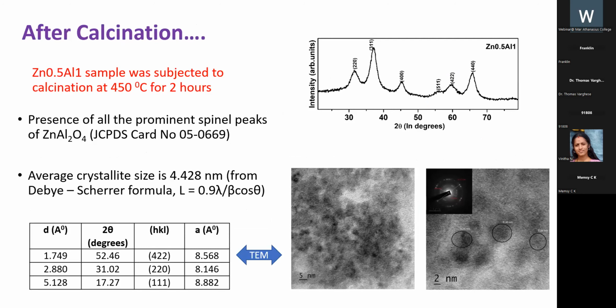Now, in order to check whether the formation is happening on calcination, we have calcined one sample, the first sample, that is with low zinc content. We calcined the sample at 450 degrees for 2 hours, and as expected, the presence of all prominent spinel peaks of zinc aluminate is observed here, which is in good agreement with the standard data. Here the average crystallite size is calculated using the Debye-Scherrer equation. It is 4.428 nanometer.